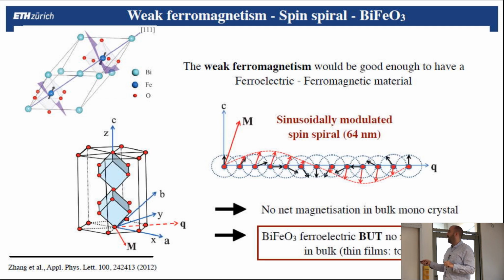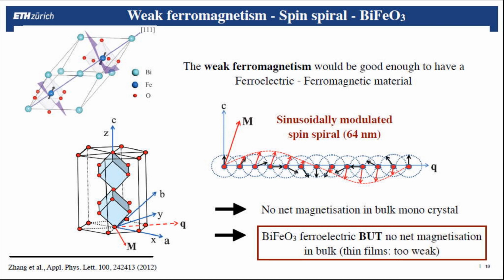But actually, there is another phenomenon that happens. If you imagine that you have your material here and you repeat it in all directions, in black here, you see what would be the antiferromagnetic direction, meaning you would have one spin going in that direction and the other one in the opposite direction. But what happens in that material is that not all of this repetition will stay exactly like this. They will rotate and do something like this, which is called a spin spiral. And that means that overall, there is no net magnetization. So even if we get a weak ferromagnetism, it's actually cancelled in the material due to this, which has a large periodicity of about 64 nanometers.